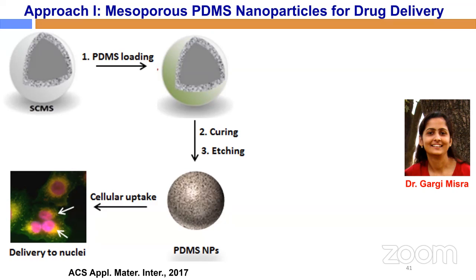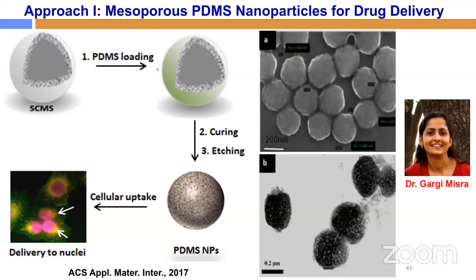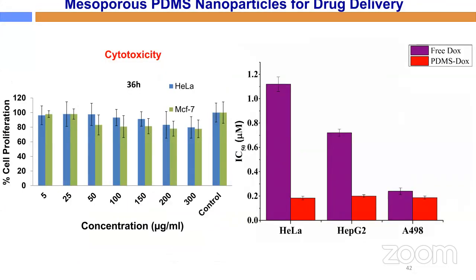With that nanoparticle, we loaded the drug and then treated the cells. The transmission electron microscope and scanning electron microscope images clearly suggest these particles are highly porous as well as very soft in nature. I say the soft nature based on the size, because under the electron beam it changes its shape. After that, we loaded the nanoparticle with doxorubicin.